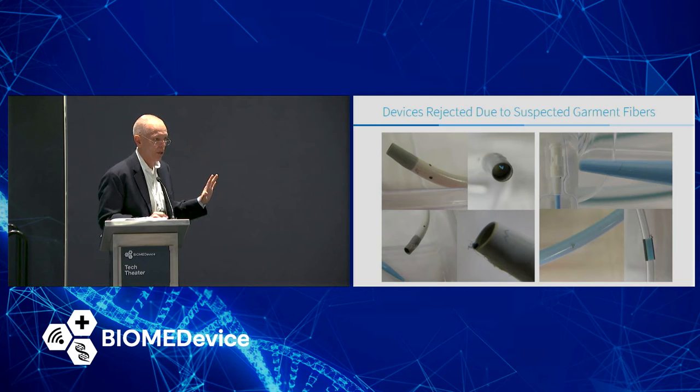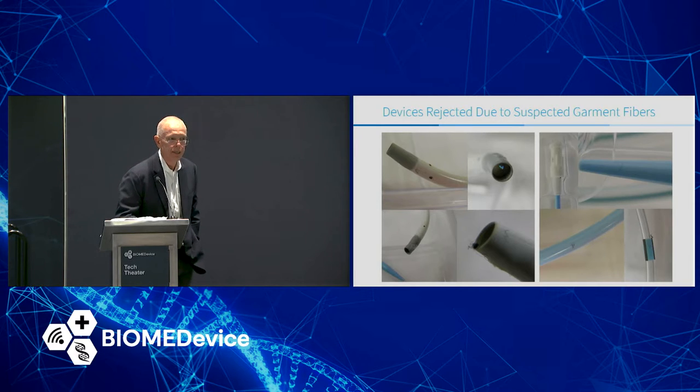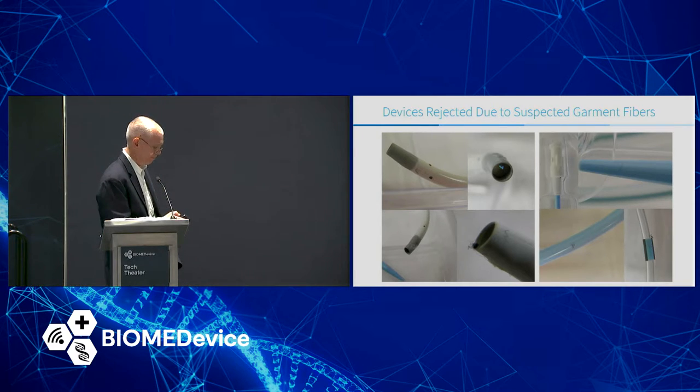Don't guess anymore. So we analyzed that, and sure enough, it was cellulose from their wiper. A lot of times, people don't realize cellulose changes color if you put other materials on it. If you put it through UV curing, you put it through heat curing, cellulose will turn brown or blue or black. And it throws you off.